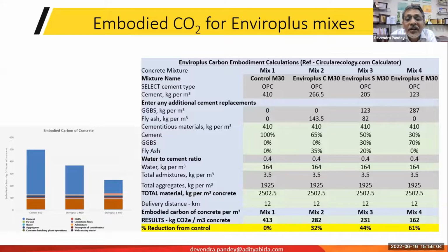So concrete itself is 413 kg per cubic meter of concrete, while in mix 2, what you see is an incorporation of fly ash within the allowable limits of the Indian standards. So the embodied CO2 reduces to 282, which is a 32% reduction. In mix 3, this is very similar to composite cement, which has 123 kgs GGBS, 82 kgs fly ash, and 205 kg cement. And what you see here is 231 kg CO2 per cubic meter, which is a 44% reduction. And then lastly, in mix 4, what you see is about 60% reduction.